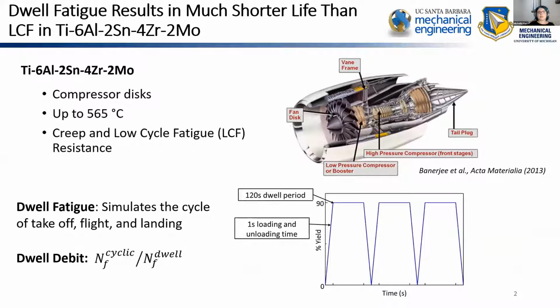So TI-6242 is used in the compressor section of jet engines up to about 565 degrees Celsius, and it's utilized there for its creep and low cycle fatigue resistance. Yet these components are known to fail unexpectedly early due to the phenomenon of dwell fatigue. Dwell fatigue fundamentally deviates from low cycle fatigue in that at the peak of each loading cycle, the peak stress is held for a set period of time. That's meant to mimic the long duration of peak stress that those components experience during takeoff and cruise. And each one of those trapezoidal waveforms represents one flight cycle.